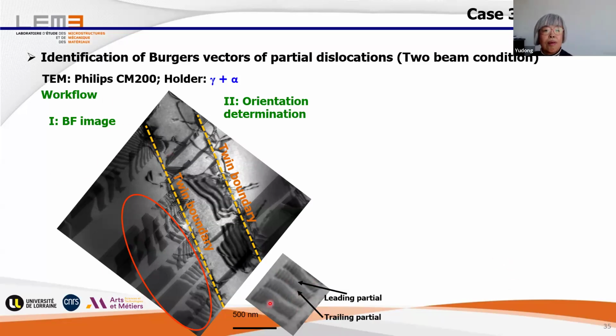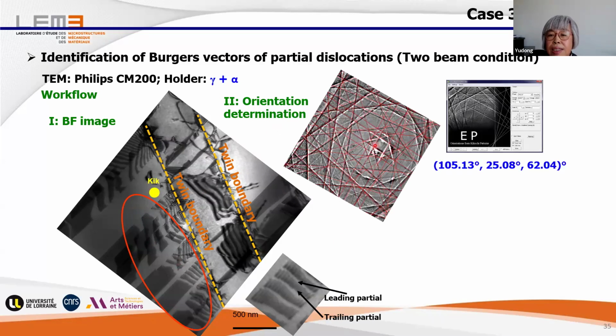Okay, and this is the first. I say something a little bit more. And then now I should analyze the orientation of this part. And then we make orientation determination. For our case, we use our magic software, Euclid's Phantasies. And then we take a Kikuchi line pattern here. And we think all these parts should have more or less the same orientation. And then you see the Kikuchi lines. With this software, we immediately have all the angles. And with these angles, we can make further analysis, because we like to analyze the two partial dislocations, the Burgers vectors of this part.